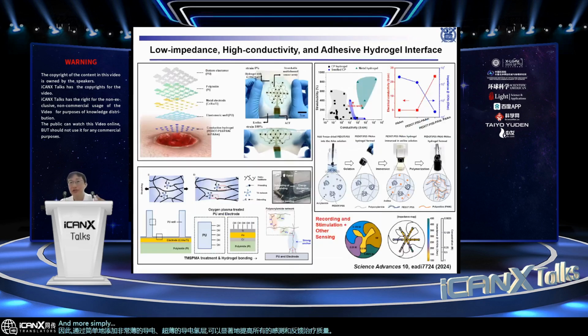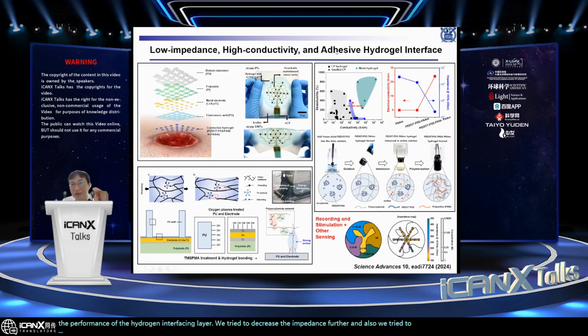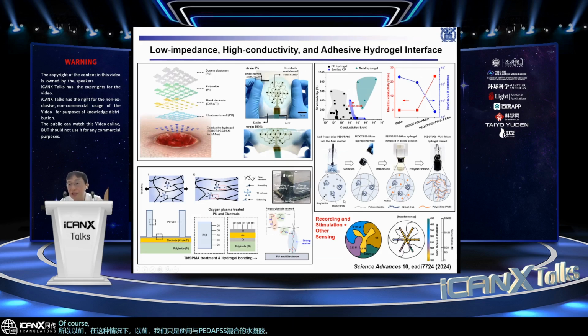And more recently, we tried to improve the performance of the hydrogel interfacing layer. We tried to decrease the impedance further, and also increase the conductivity further, and also improve the adhesion property of the hydrogel interface further. Let me explain one by one. So previously, we just used hydrogel mixed with PEDOT:PSS. Of course, in comparison to bare hydrogel, this conducting hydrogel has higher conductivity and lower impedance, but still it can be improved further.